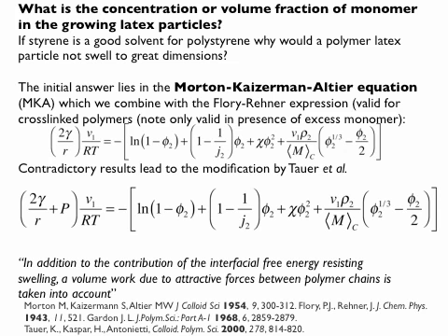Now, this theory works relatively well. However, there are some people that say, well, it's not perfect, and sometimes some corrections need to be made. As a result of that, I put one of these question marks on the equation as well. And you can see that Klaus Tauer, for example, said, okay, in addition to the contribution of this interfacial free energy, I also have to do something with attractive forces between polymer chains. So you could argue that that term has to be in the interaction parameter, which is a constant, added to this equation.